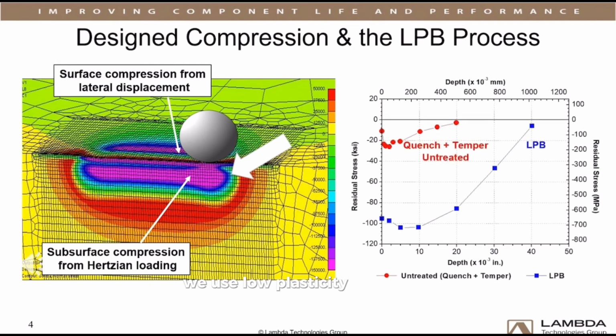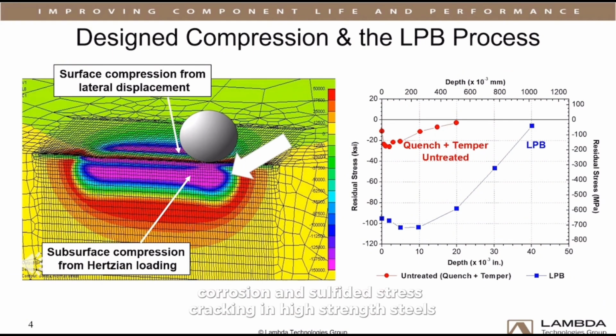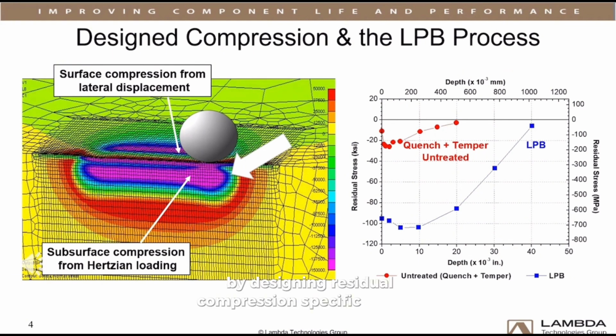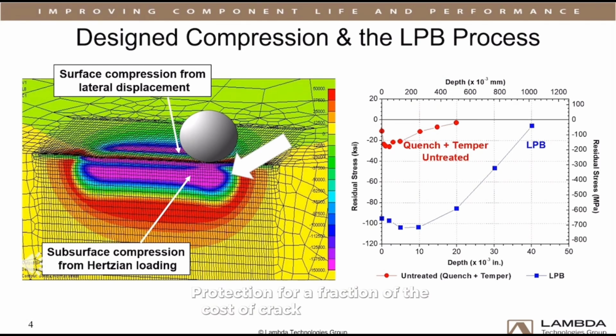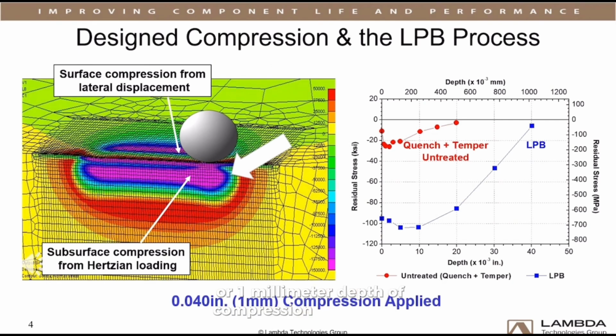We use low plasticity burnishing to introduce engineered compression. LPB has been shown to eliminate stress corrosion and sulfide stress cracking in high-strength steels. By designing residual compression specific to each application, LPB provides superior protection for a fraction of the cost of crack-resistant alloys. In this application, a 40,000th of an inch, or 1 millimeter, depth of compression was applied with low cold working, minimizing general corrosion in addition to sulfide stress cracking.